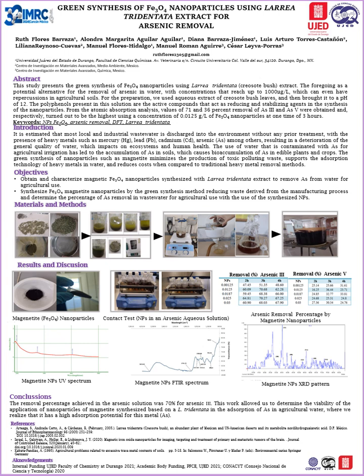The strong bands at 1741.15 and 1477.8 are identified as amide 1 and amide 2, which arise due to stretching vibrations like the union of a carbon and oxygen with a double bond group with the nanoparticles. The peak at 1423.11 is attributed to the asymmetric and symmetric C-O stretching vibration of a negatively charged carboxyl group.